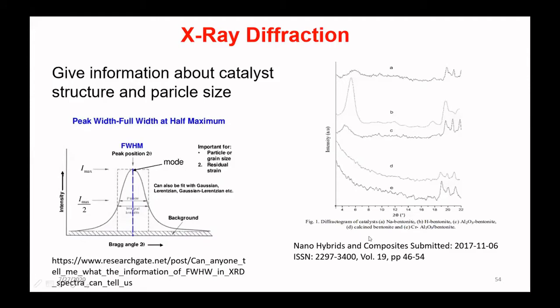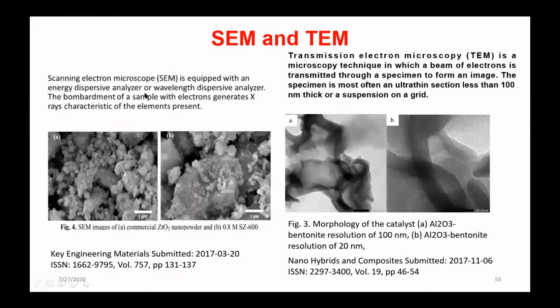Scanning electron microscope is good with the energy dispersive analyzer, or wavelength dispersive analyzer. Bombarding the sample with electrons generates X-rays characteristic of the elements present. Actually, the principle of these instruments is like an optical instrument, but we use an electron gun instead of visible light. We can see the morphology with the SEM. It's a very good instrument to observe cracks, for example, in materials.